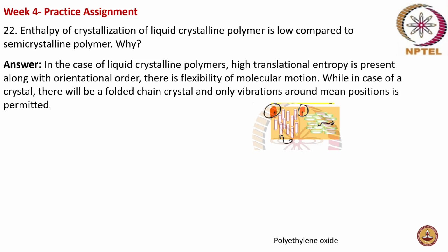So, in case of liquid crystalline polymer, it actually has higher translational entropy. Okay, whereas there will be an orientational order. If you just look into this liquid crystalline polymer, there is an order in the orientation, but once you have this crystal structure formed, the orientation is kind of fixed. But still, you will be having translational entropy. That is, this block can move between this region and this region. Similarly, this block can move from this region to this region. So, these can still move, but the overall order, this kind of a vertical order, will remain the same.